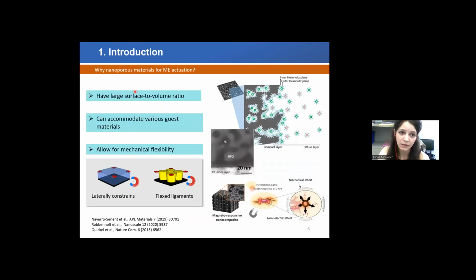And recently, nanoporous materials also become attractive for the magnetoelectric actuation due to several reasons. One of them is their large surface to volume ratio. That is extremely important for some magnetoelectric applications where we need to accumulate a large amount of charge at the surface, or when the material is immersed in a liquid electrolyte and then the porosity facilitates the formation of the double electric layer all over the surface and inside the pores.